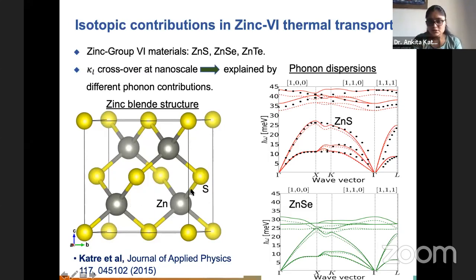This is because this acoustic-optic gap basically comes from the mass difference of the constituent elements. So zinc and sulfur have different masses. The mass ratio is around 2 in this case, so that's why we see a bigger gap here. And for zinc selenide, there is no gap because it has almost the same masses of zinc and selenium. That is another thing we need to know. And for zinc telluride, there is an acoustic-optic gap as well, because it also has a mass difference.